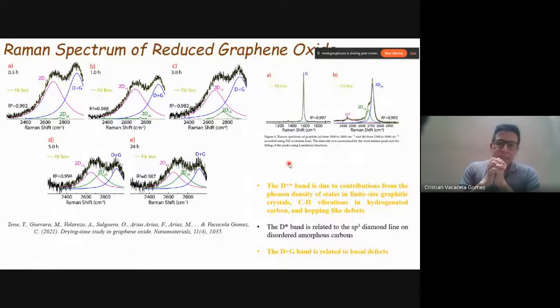Now, let me focus. We are just near the end of this presentation, but please just give me a few minutes to finish. Let me focus now on the 2D band region. If you remember, in the graphene oxide we have the 2D band, 2D 1A, 2D 2A, and the extra peak is the D plus G. And again, when we start with the reduction process, the interesting thing is, for example, compared with 0.5 hours of reduction, after 24 hours the intensity of the 2D 2A band increases and the intensity of 2D 1A is reduced.